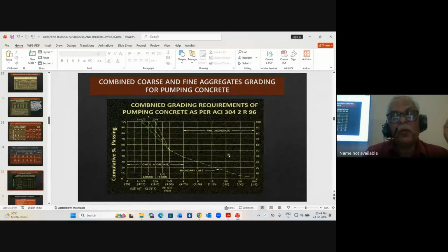What is more important in pumping concrete? Of course, if you go to the Indian standards, for pumping concrete it asks you to reduce the fine aggregate by about 10%. But if you go through some ACI 304.2 standards, it gives a specific grading starting from higher size aggregate to a combined grading.